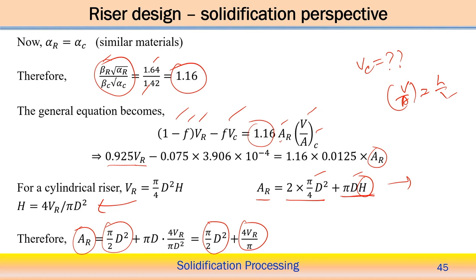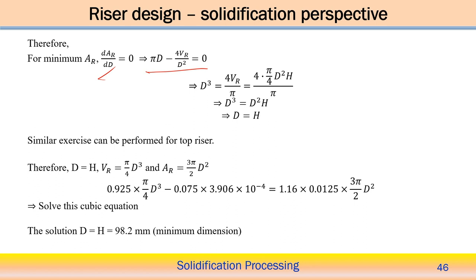Here one term should not be pi, it should be d: the pi balances, and with the 4 here, one d will be there. So instead of the pi it should be d. Then do the first derivative and we can find this expression. From there, with 4 Vr by pi, using the value of pi by 4 d square h, finally we are getting d equals h. So for minimizing the heat transfer rate on the riser, the diameter should be equal to the height in the case of the side cylindrical riser.